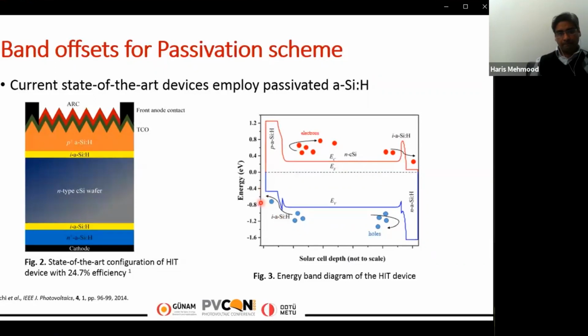However, there are challenges associated with this type of device, such that because of some high energetic carriers, electrons may jump this p-type amorphous silicon barrier and may recombine with the holes, thereby increasing the recombination of the device, and ultimately leading to a reduction in the photovoltaic performance.